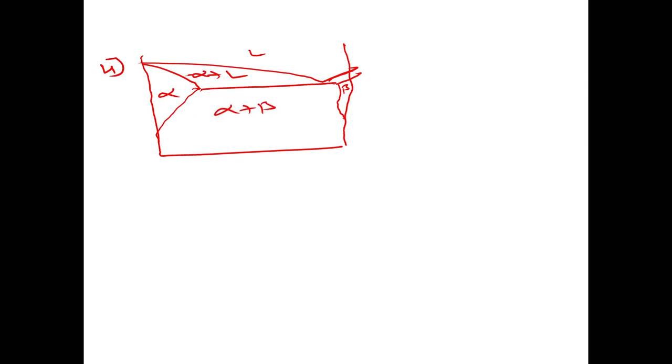One thing that we can observe in all phase diagrams: when you keep the temperature constant, and this is composition, and you travel from left to right, you will get single phase, plus double phase, plus single phase.